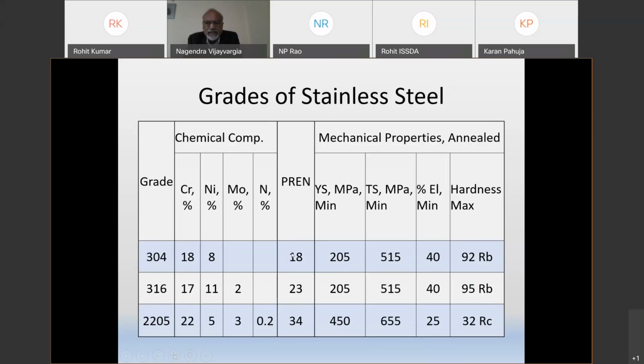In 304 grade, it is 18. This number is derived by an empirical formula using chemical compositions, how much of each chemical is present. So 18 is for 304, 23 is for 316, and 34 is for 2205. However, if you see the grades, the mechanical properties of 304 and 316 are the same, only hardness is a little higher, 95, whereas in 2205 elongation is low, but yield strength and tensile strength are higher. Hardness is much higher compared to this, 32 RC, because it is on another scale.